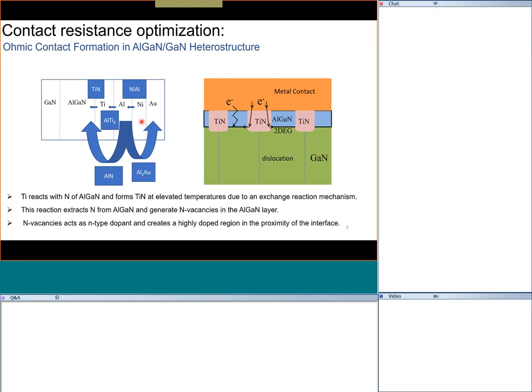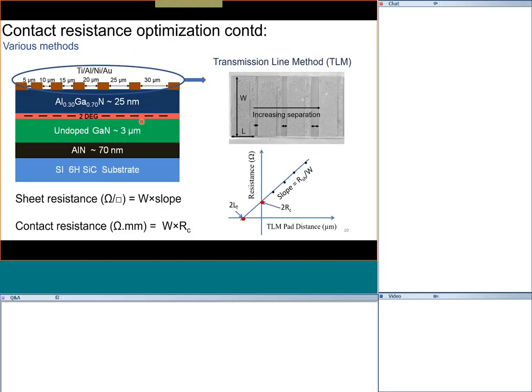Each and every metal in the stack has an important role. The ohmic contact alone has probably more than a thousand published papers. We started working on ohmic contacts about a decade back and are still trying to improve them because they are that important for RF devices. To extract important metrics of ohmic contacts, we use a TLM (transmission line measurement) geometry — contacts at specific spacings like 5, 10, 20 microns — measuring IV characteristics and plotting resistance as a function of separation.